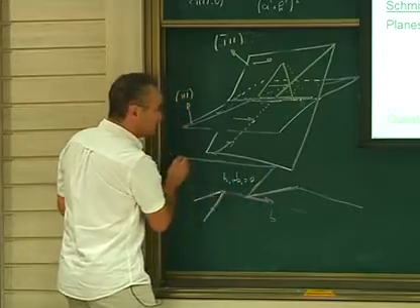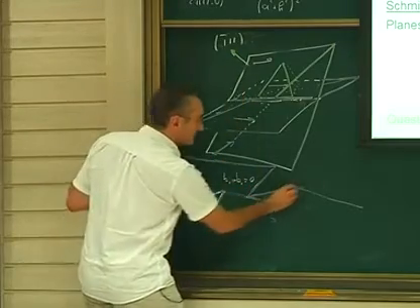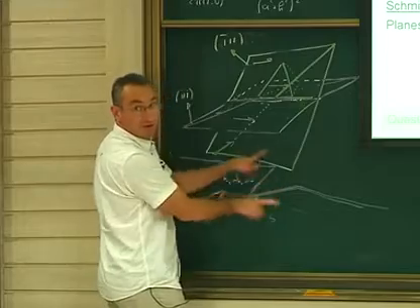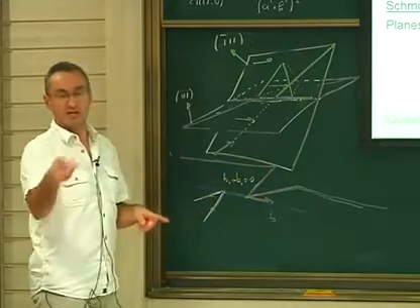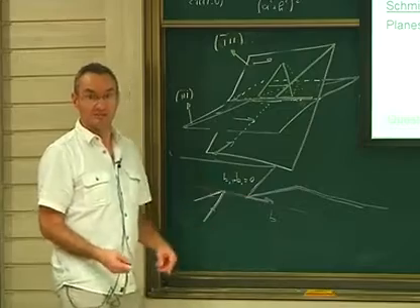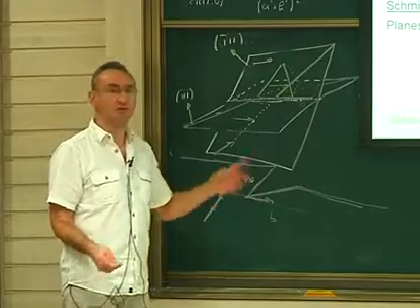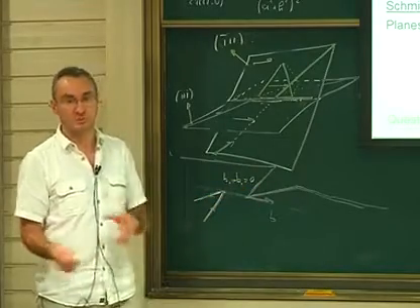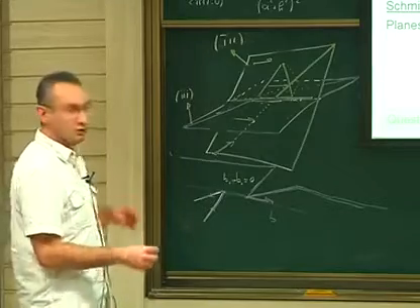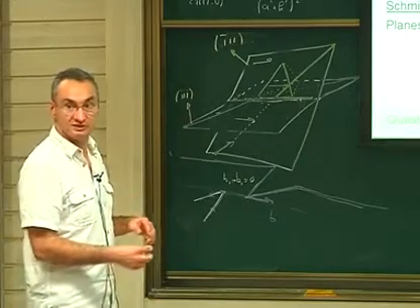You have one kink which is going in a 1,1,1 plane, another kink going in another 1,1,1 plane, and here you have the two edge segments which build a cross kink. Yes, what I explained yesterday as the open source mechanism. You're right. It is exactly that. Except that this was for FCC. So for FCC we don't speak about kink. Kink is more for BCC. For FCC we speak about collinear junction. Okay, but that's true.